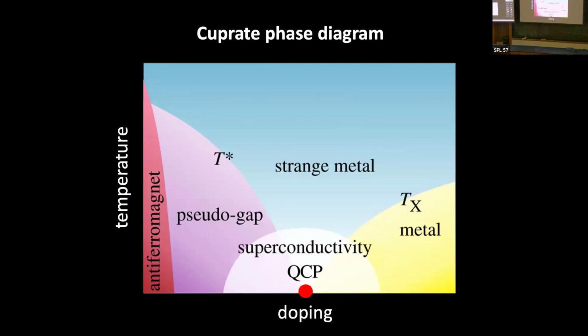So there's now spin ordering in the system. This comes from a process known as superexchange, where an electron hops over to a neighboring site and then hops back. You saw in the Hamiltonian, there's no direct interaction between particles in different sites, but you can have a second order process where you hop and hop back. So that goes as the tunneling squared over the interaction. And this leads to an effective spin-spin coupling on these different sites that's antiferromagnetic in nature and leads to this antiferromagnet. So these two phases, the Mott insulator and the antiferromagnet, are known to exist in the cuprates. They're known to exist in the Hubbard model, where we can do simulations quite accurately with a technique known as quantum Monte Carlo at half filling. So they're basically good phases to benchmark our quantum simulator on.